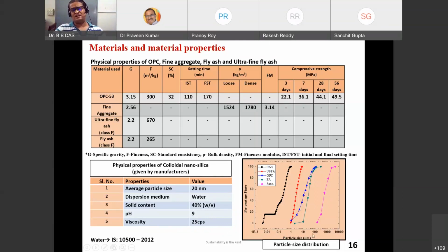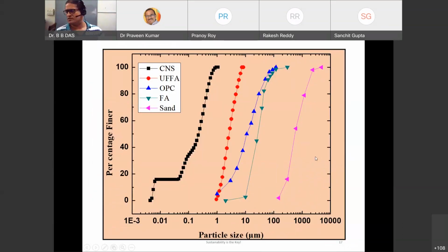And this is the particle size distribution of all the materials, starting from the sand, because we work with water, sand, fly ash, ultrafine fly ash, then the cement, and then the nano. So this is the modified, or you can say expanded, version of the particle distribution. You can see the nano silica is extremely to the left, almost a single size. And then ultrafine fly ash, also a single size of particles, then fly ash, then cement and the sand.